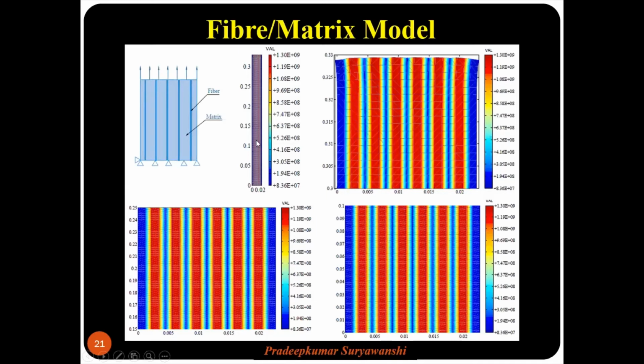Okay, so this is the mesh of that particular cantilever beam which we simulated. In this fiber matrix model, we assigned the fiber properties to the column, which indicates fiber in that model, whereas we assigned matrix material properties to the springs which represented matrix in this lamina. There is an individual assigning of the material properties like this, and we performed the simulation under a tensile test under displacement control. These figures indicate the exaggerated portion of the top, shown here, middle, shown here, and bottom of this, shown here.